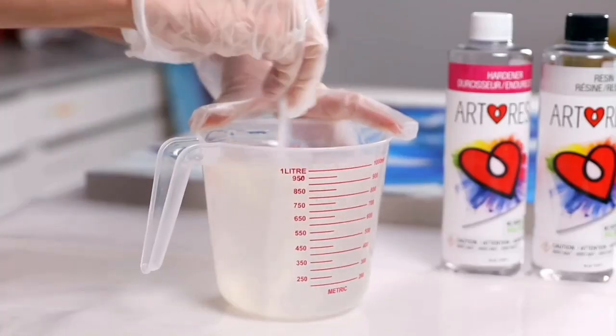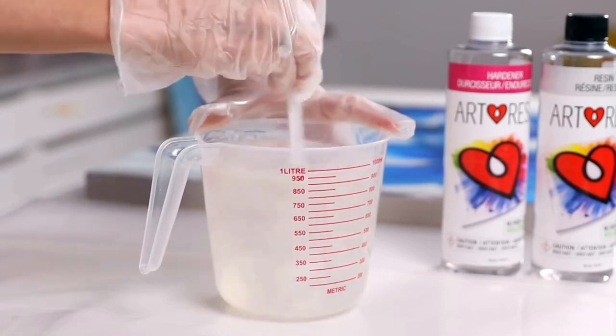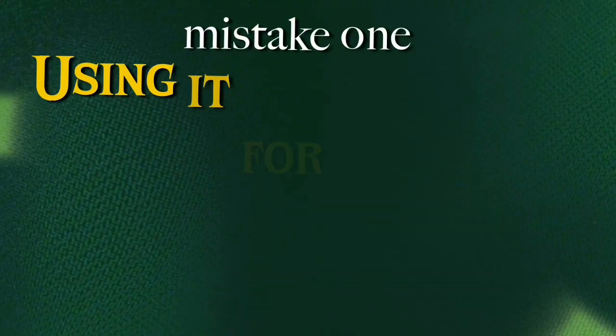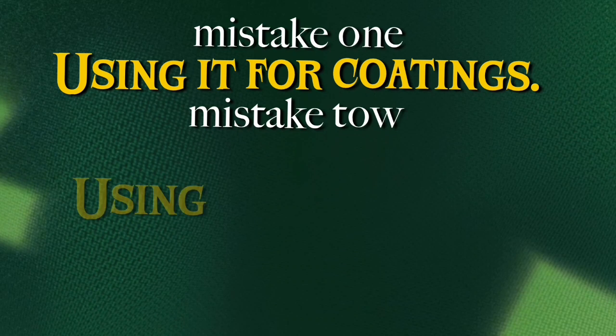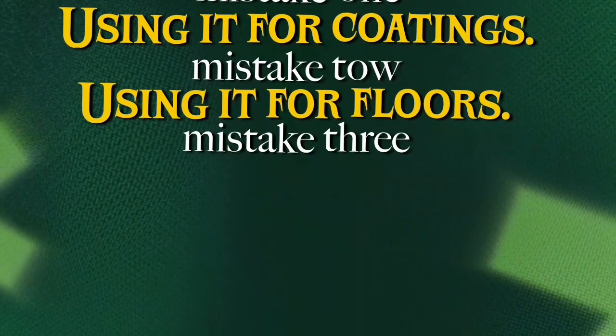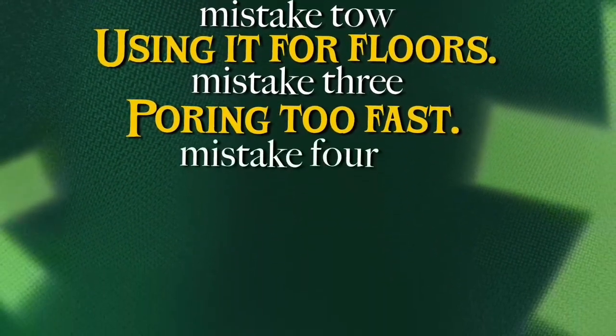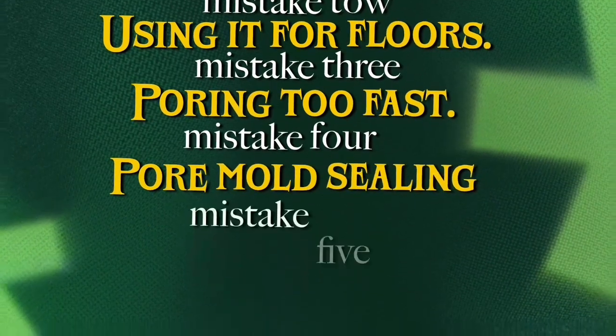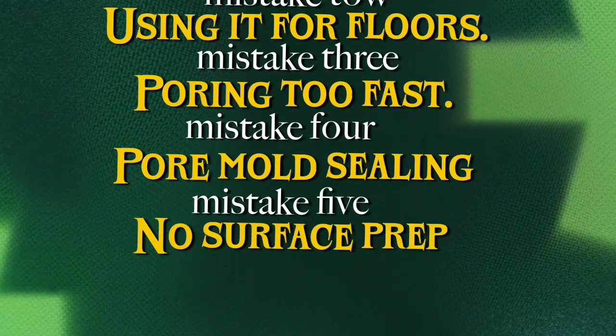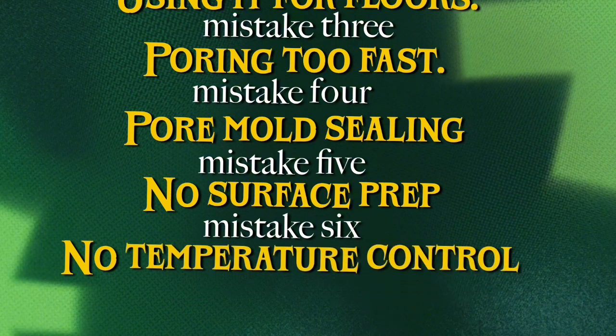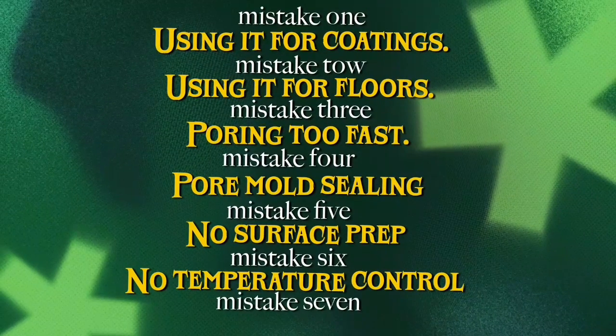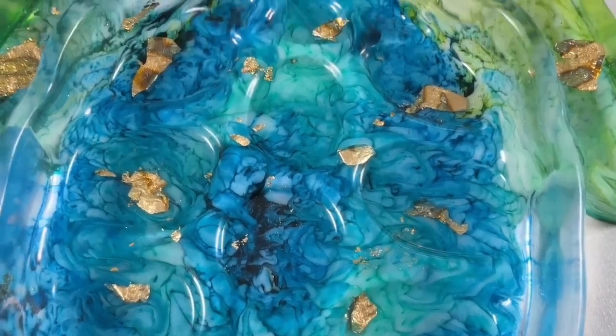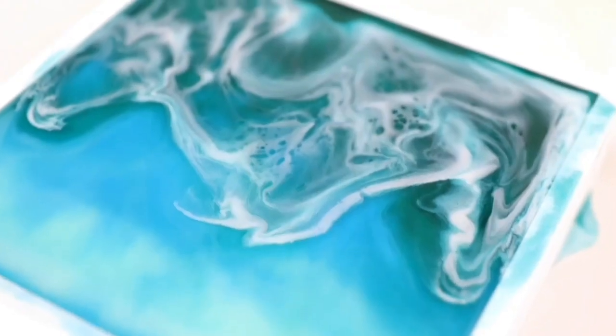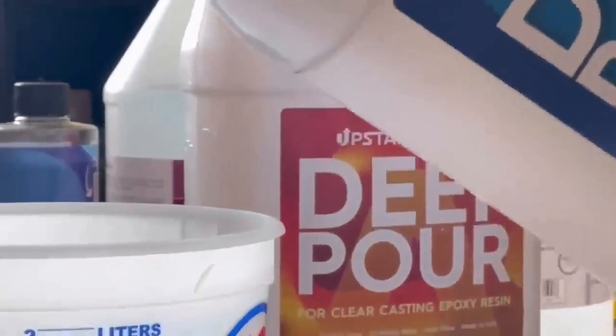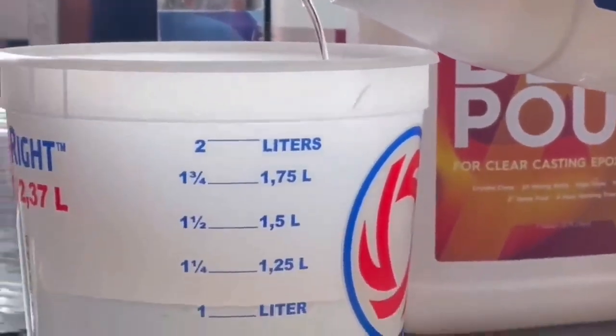Common mistakes with deep pour epoxy. Let's protect you from mistakes. Mistake 1, using it for coatings. Mistake 2, using it for floors. Mistake 3, pouring too fast. Mistake 4, poor mold sealing. Mistake 5, no surface prep. Mistake 6, no temperature control. Mistake 7, no test pour. Deep pour epoxy still needs surface prep, clean molds, sealing, mixing accuracy, environmental control. Slow curing does not mean careless work.